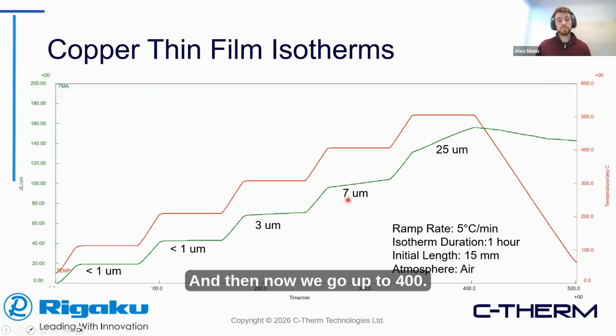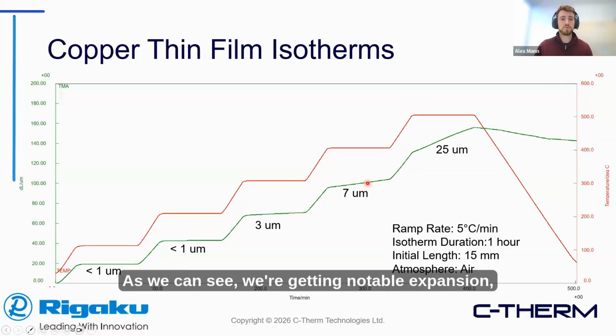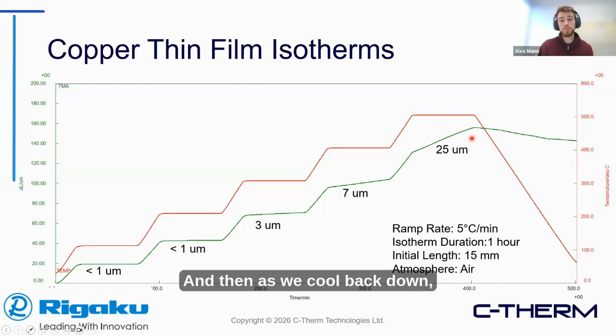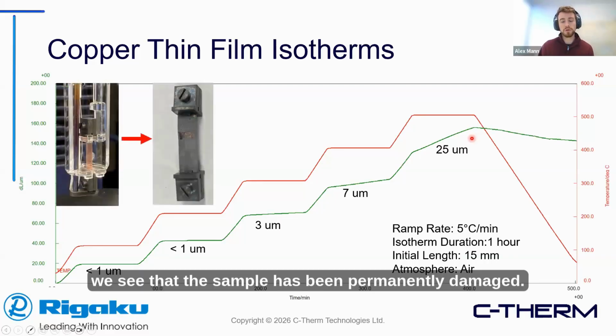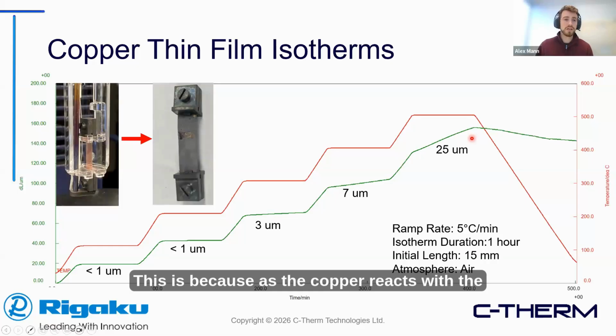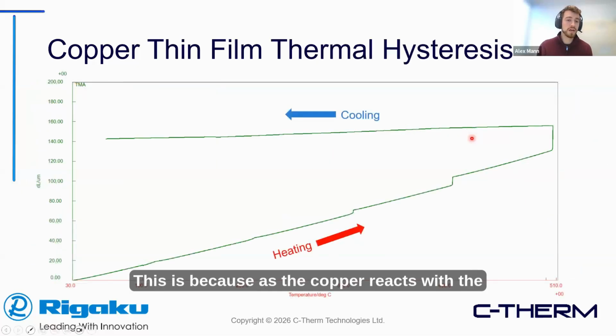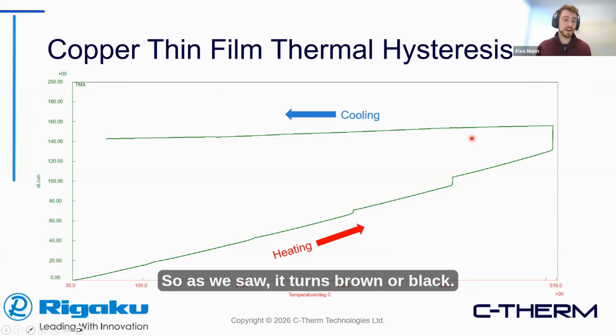Then we go up to 400. As we can see, we're getting notable expansion, even though we're not increasing the temperature. Lastly, the last isotherm shows a huge amount of expansion. Then as we cool back down, we see that the sample has been permanently damaged. This is because as the copper reacts with the air, it tends to oxidize. As we saw, it turns brown or black.